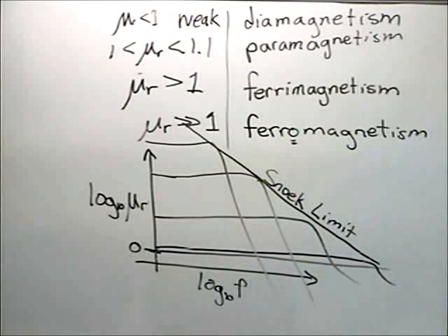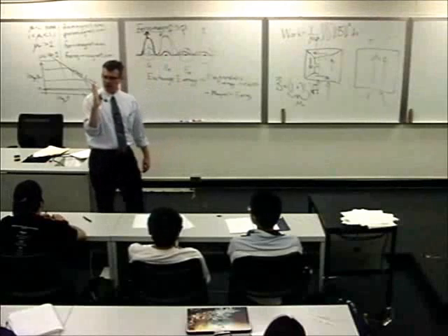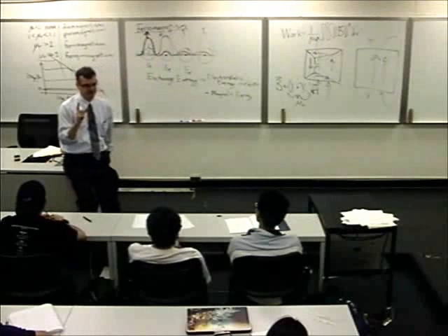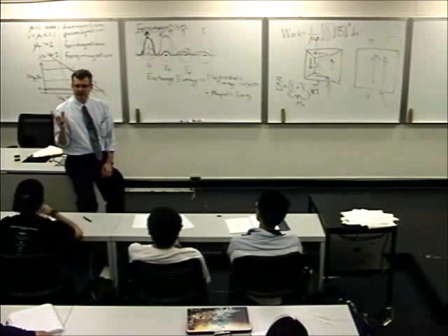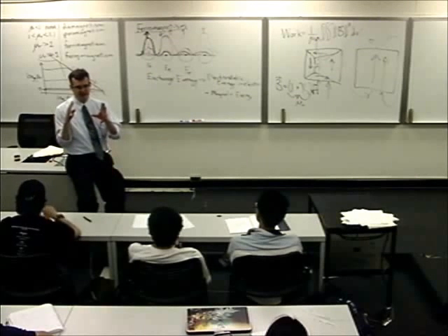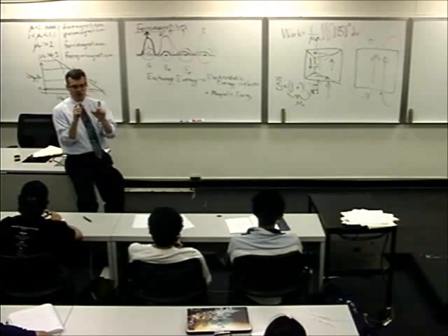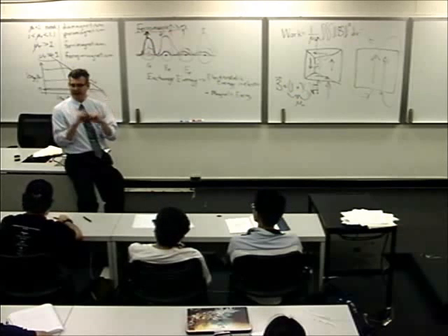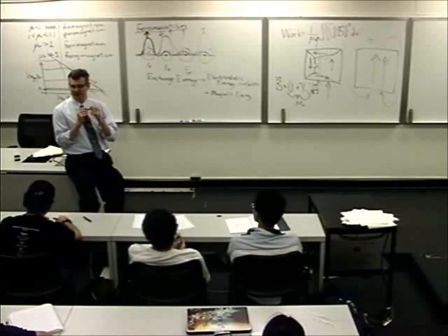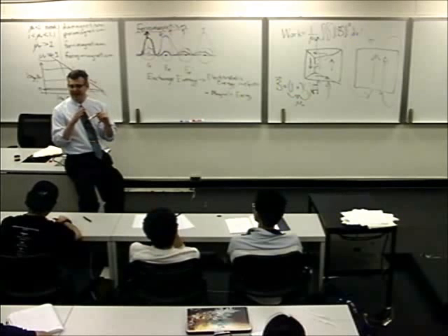Now, there are a couple ways that you can get around that. One is to make some nanoparticles that have a special distribution of their diameter. Turns out if you take a ferromagnetic material and you get that chunk of material somewhere in a sweet spot between, say, 10 and 30 nanometers of diameter, that particle becomes what they call a superparamagnet. My students used to joke and call this superparamagnetism, and then they always add expialidocious.